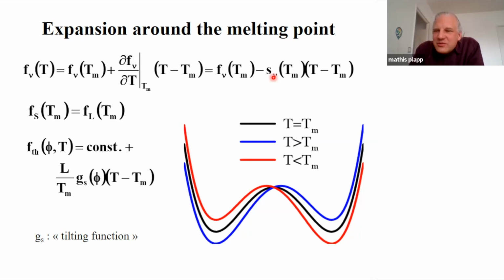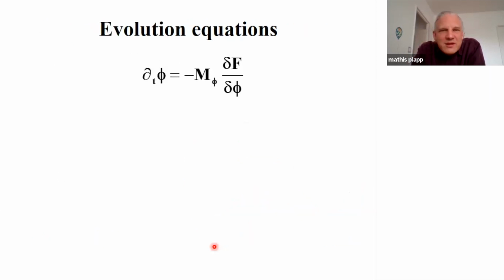Because, as I've said, when the two phases are in equilibrium, this is the black line, then the two wells are of equal depth. If I add the thermodynamic temperature energy in this form here, if I'm above the melting temperature, well, then the favored phase is the liquid. So the well is tilted to one side. And if I'm below the melting temperature, then the favored phase is the solid, and then I'm tilted in the other way. Okay. So everything works fine for the thermodynamic coupling. The temperature just tilts the double well in one way or in the other, which will make the interface go one way or the other.